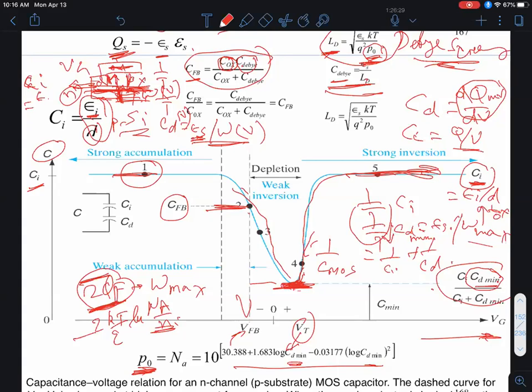This is a very important curve, and I wanted to study that thoroughly because there's so much information that you can get. From the shape of the curve, you can also get the doping type, because it turns out, in this case, it's a p-type doping, and you can tell that because in the depletion region, the curve will go down slowly, but then once I hit inversion, it'll go up steeply. On the other hand, if it's n-type, it will be the mirror image.